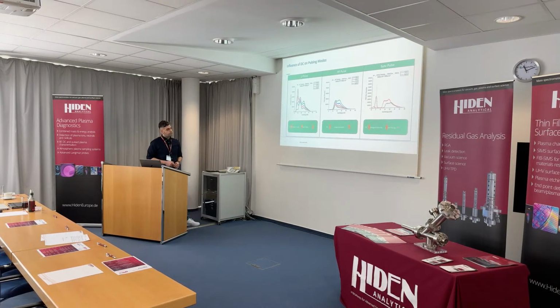And this is the influence of duty cycle on pulsing modes. As the duty cycle increases in LF pulse, the higher energy range integral intensity increases, and in the lower energy range, it decreases. But in case of HF pulsing, the integral intensity of the whole IDF increases, and in case of sync pulsing, the integral intensity increases and the lower energy range is not available.